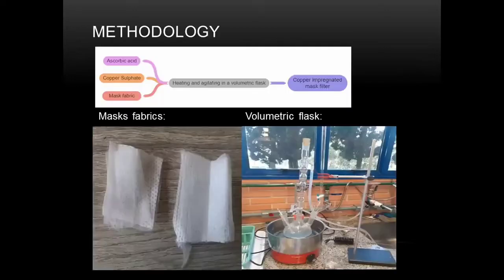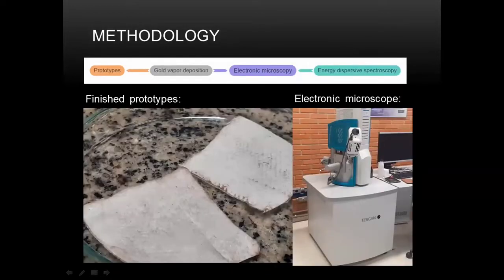The methodology: we isolated copper particles from copper sulfate solution with constant heating in a volumetric flask, simultaneously impregnating pieces of TNT cut from commercial disposable protective masks. Here you can see the process and the images of this experiment. The fabric pieces were removed and left to dry in an oven for 24 hours, and after drying, the fabric pieces were placed in Petri dishes and sealed to avoid contamination. Samples of the TNT pieces were analyzed by SEM, scanning electron microscopy, and EDS, energy dispersive spectroscopy, after impregnation of a gold layer by PVD, physical vapor deposition.